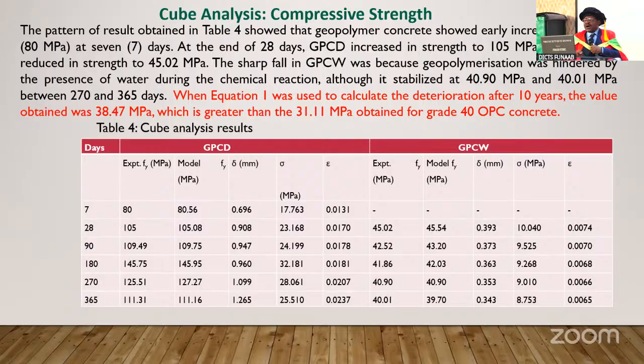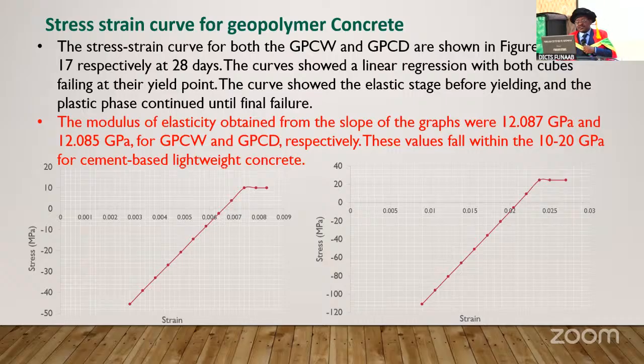When equation 1 was used to calculate the deterioration rates at 10 years, the value obtained was 38.47 MPa, which is greater than the 31.11 MPa obtained for grade 40 of the ordinary Portland cement concrete. We were able to use the stress strain curve to predict the modulus of elasticity, and it was discovered that the modulus of elasticity was between 12.08 and 12.085, which falls within 10.0 and 20 GPa for cement-based lightweight concrete.